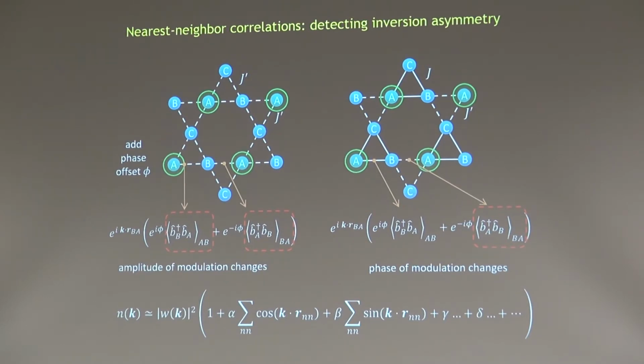So it's like taking a 2-slit pattern in optics and putting a little bit of a phase shift on one of the slits. You'll see that your optical interference pattern shifts sideways when you do so. So we're looking for a signature of that shifting sideways, and that would indicate that it's just one of these 2-slit interferences that's visible in our data. If at the same time we had also picked up a strong signal from coherence on the other bond, that would have produced an interference pattern that equivalently slides in the other direction. And if they were of equal strength, then the displacements would cancel.